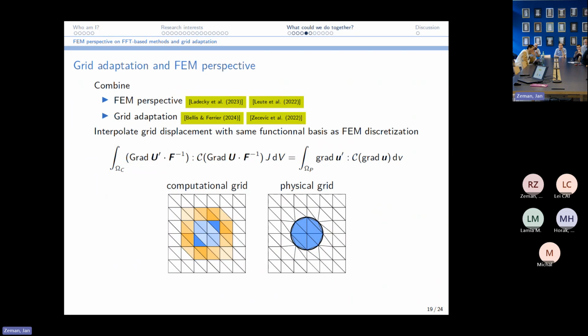So what we are trying to do now is, if we have some heterogeneous media in which you have heterogeneities which have shapes that do not fit this regular grid, and you discretize it without too much care, you will introduce some oscillations near the boundary of the constituents. So what we're trying to do is to move the nodes near the boundary to have conformal elements. And that combines very well with what is done here about this FEM discretization combined with this FFT-based homogenization.